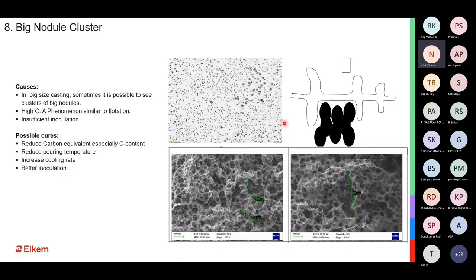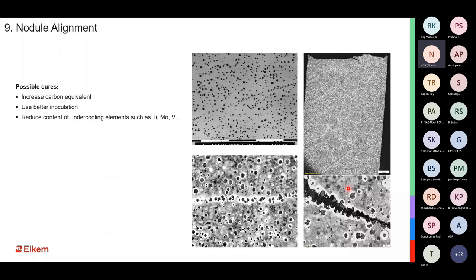And how do you solve it? One, like every other problem, we solve it by getting a much better carbon equivalent, by reducing the pouring time, thereby not giving it too high a pouring temperature, thereby not giving it enough time and heat for the segregation. You increase the rate of cooling. And of course, if you are better in terms of inoculation, you'll be better in terms of graphite precipitation. You will not have a lot of dendritic growth, and thereby you avoid this kind of phenomenon where the graphite gets trapped within the dendritic arms. So that can be one of the solutions.